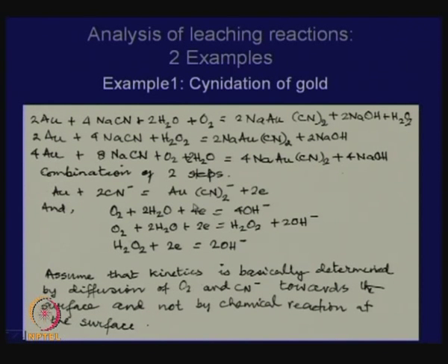Now, try to understand why we are doing cyanidation. You may say, you know, gold is gold, it is always in free state and all that, but that is not so. Gold is found after mining embedded in rock surfaces. It is not in free state, it is locked with all kinds of things. So, the entire crushed and ground rock is treated by cyanide solution, and gold is taken out of the whole thing into a solution, not as gold ions, but as gold cyanide ions.